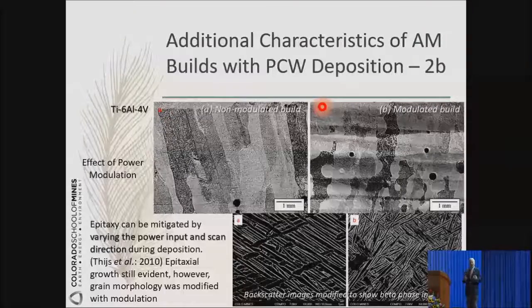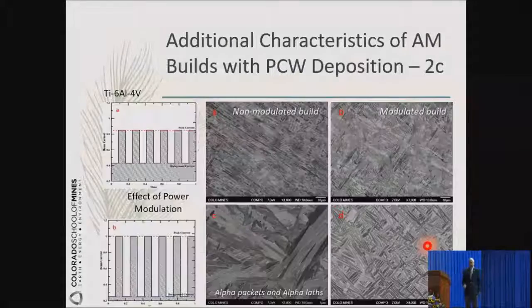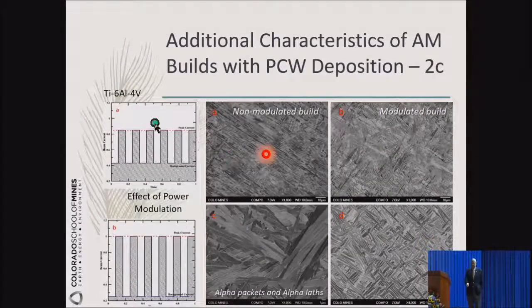And that is all by modulating the current, okay? And the finer microstructure also shows that there is a refinement of the grains. So that is great. So here on the left-hand side, you have the pulsing of the currents. And then on the right-hand side, you see here, going from non-modulated to modulated, you have a refinement of microstructure. Again, I'm showing you that it is possible to change the macrostructure as well as the microstructure.